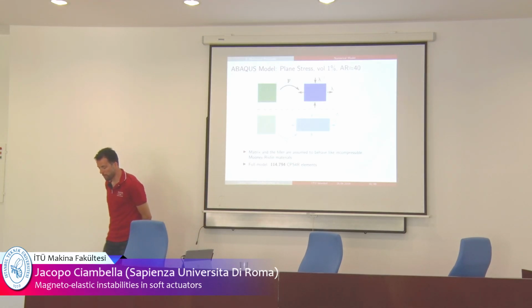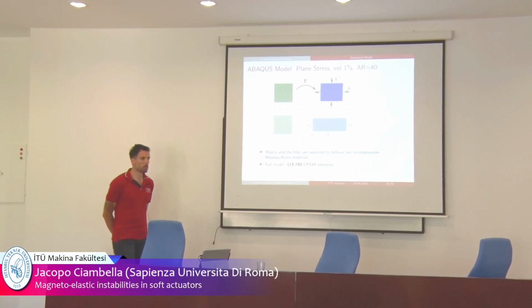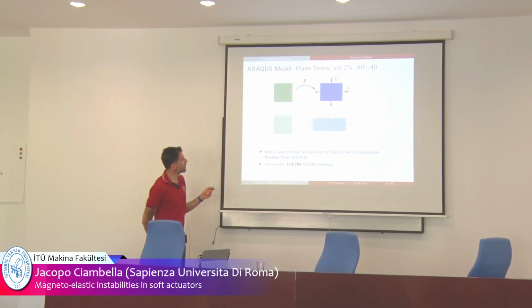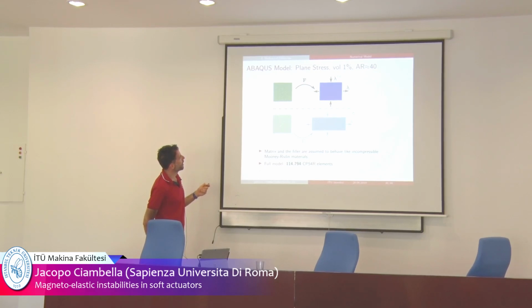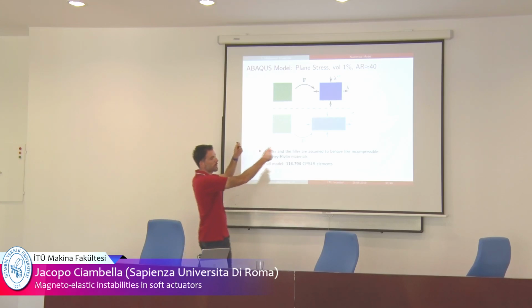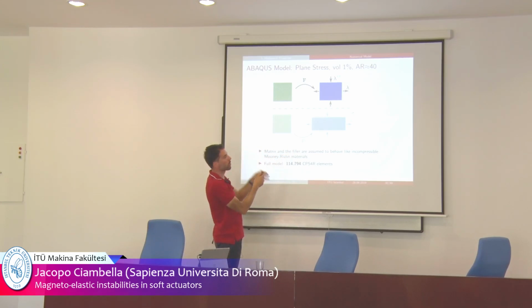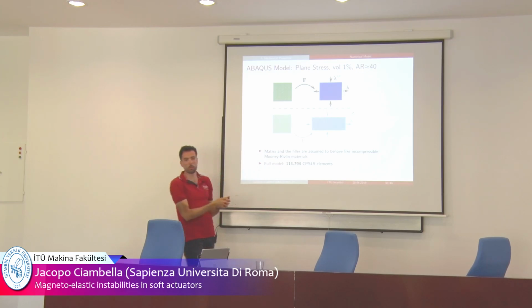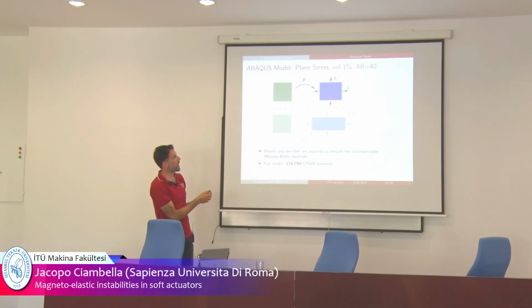We did multi-scale modeling in Abaqus. What we did was that you have these representative volume elements with a lot of fiber inside. You apply a deformation F, which is simple extension. So you pull in this direction, lambda is the stretch here. And because the matrix is incompressible, you have lateral striction of the specimen.